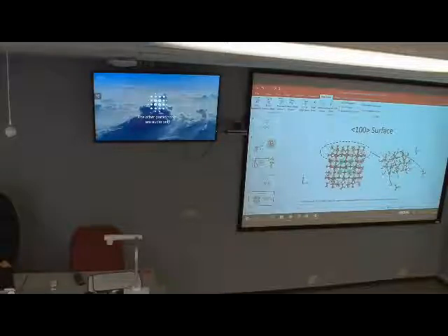So when I do my binding energies, I include the protonation effect too, because it's not going to deprotonate and then just stay as a charged anion. It's going to want to take a proton from somewhere, or get rid of its charge somehow. And so when I do my binding study, this is just another figure of the model, I consider binding to the 1,0,0 face of the surface. If you just take this and rotate it, that's what this figure is showing. I remove the acetate anion from the center face, and then one of those protonated amines from one of the adjacent spots that are covering the face.